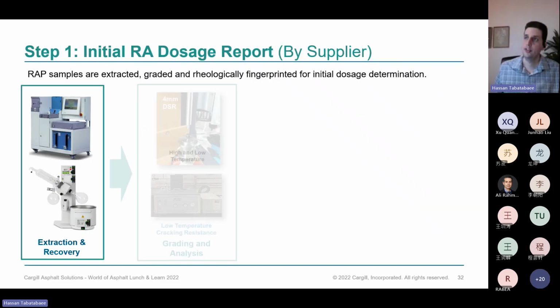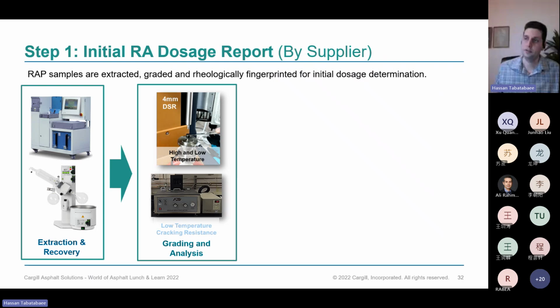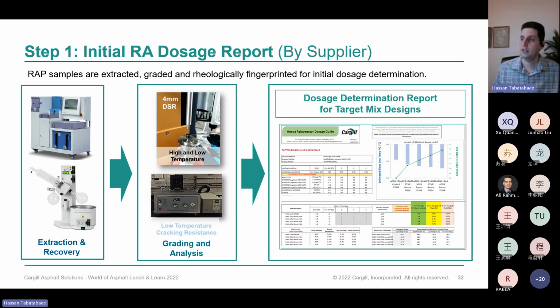The dosage determination is going to be done generally by classification of the recycled asphalt binder with extraction recovery, looking at either penetration, low temperature properties, or various rheological aspects. And then using that, you can determine how much dosage of additive is needed to get, say, a standard mix that maybe only has 10% wrap to get to like 15, 20, 30, 40% wrap while maintaining the same properties. That can all be calculated by determining the properties of the basic asphalt binder and the wrap that would be used in it.